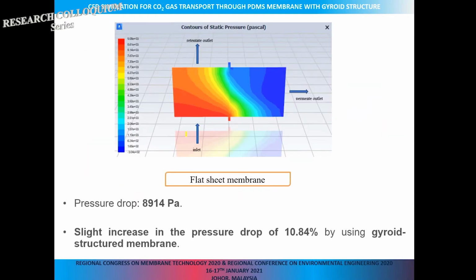Meanwhile, for the flat sheet membrane, the pressure drop is slightly lower compared to the gyro structure membrane. The profile is also slightly different, but we can say that the pressure distribution is slightly more uniform as compared to the gyro structure membrane. In comparison, we can observe that there is a slight increase in the pressure drop of up to 11% by using the gyro structure membrane.